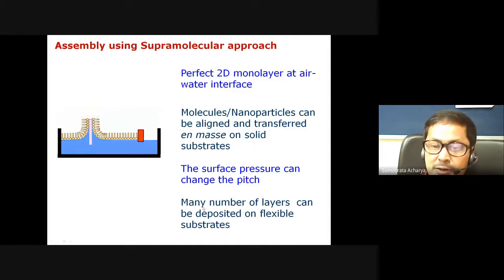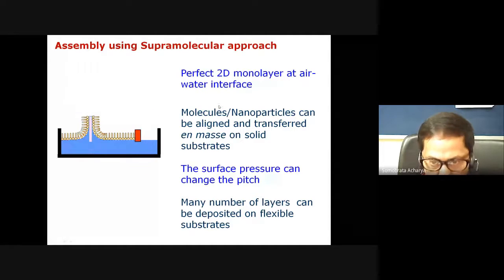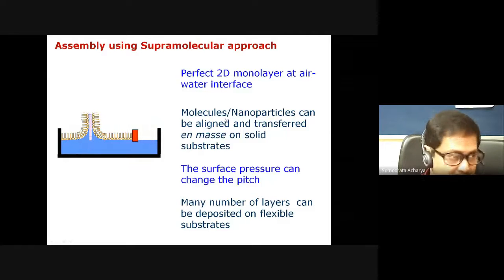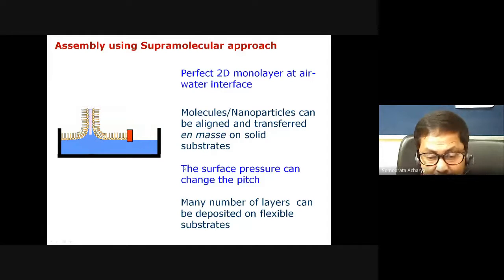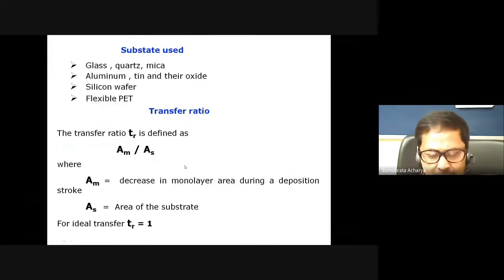The advantage of the technique is that a perfect molecular two-dimensional interface can be formed, and molecules and nanomaterials can be aligned and transferred onto the solid substrate. I have shown that one. And the surface pressure can change the distance between the nanomaterials or molecules, which is called the pitch. So you can control the pitch, and you can deposit many layers there. Okay, and you can basically measure the transferred molecules or nanomaterials by calculating the transfer ratio. That is done by means of the ratio of the transferred area and the area of the substrate.